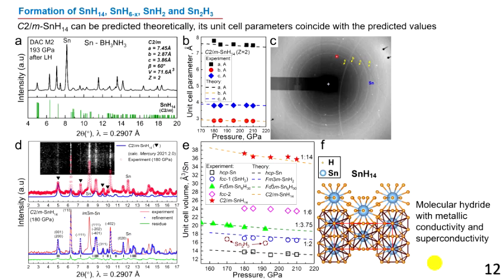In addition to the main product SnH4, we have synthesized several new tin hydrides, including higher polyhydride C2/m SnH14, which was predicted using the theoretical methods. On the panel A and on the panel D, you can see the experimental X-ray diffraction pattern for this compound and the theoretically predicted one. You can see the correspondence between the theory and experiment is quite good, and theoretically predicted unit cell parameters and volume are in quite good agreement with experimental ones. As well, we also synthesized several lower hydrides such as SnH2 and Sn2H3.